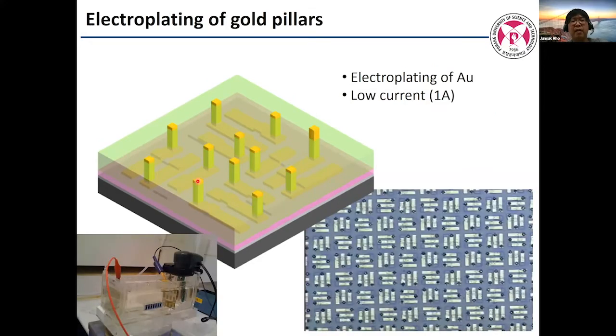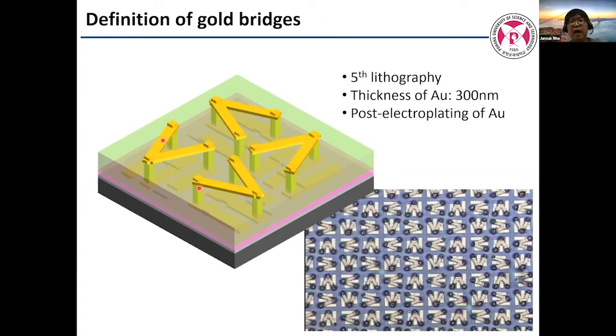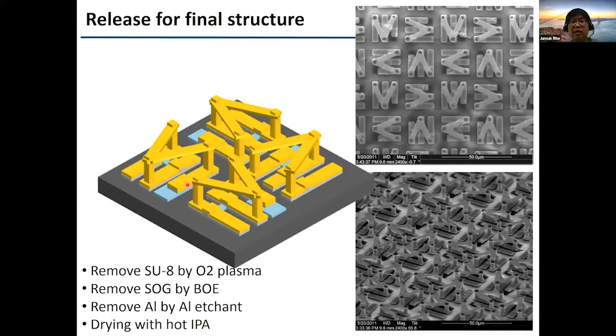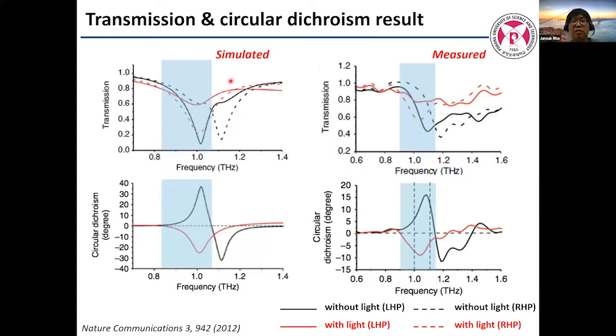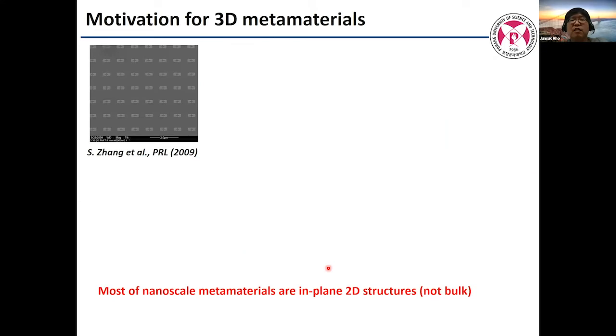So coming up is the fifth lithography, making the top structure of a V-shaped antenna. And then we do a little micro welding here to make the connection between this pillar and this final antenna. And then lift off, and it's done. So this is a micro scale metamaterial working in terahertz frequency with negative refractive index. It was published almost 10 years ago. Experimentally, it's very easy to do that. So we confirm negative refractive index exists.